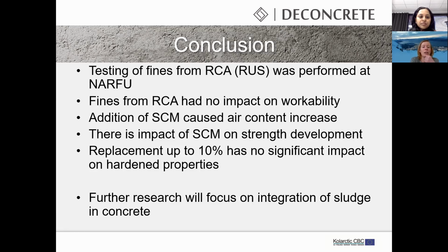And then, as I already mentioned, the impact of supplementary cementitious materials on the strength development: with all the supplementary cementitious materials, the strength after 28 days is still developing and doesn't reach 100% of the provable or significant strength. And the 10% replacement has no significant impact on the hardened properties, and also might be a sustainable replacement ratio for the concrete production without any significant impact on the properties under industrial production.